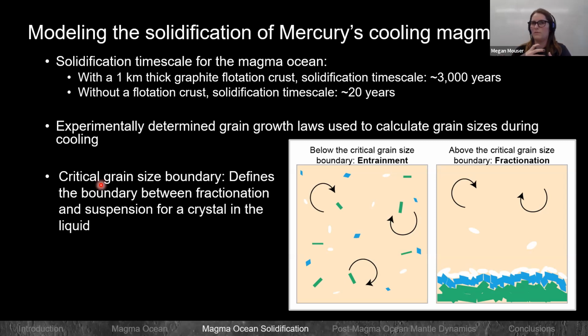So if your grain sizes are small enough and the density difference isn't great enough between the crystal and the liquid, they will remain suspended within the liquid, and you end up with this entrainment type scenario, which is like batch crystallization. If you have grain sizes that are large enough, and the density difference between the crystal and the liquid is great enough, they can efficiently fractionate from the liquid itself. Depending on the density of the crystal, you could have sinking. So if it's denser than the liquid, you have sinking. But if you have something that's lighter, that's where you start to get that flotation process. So this is an important way to define what type of crystallization process we're looking at.